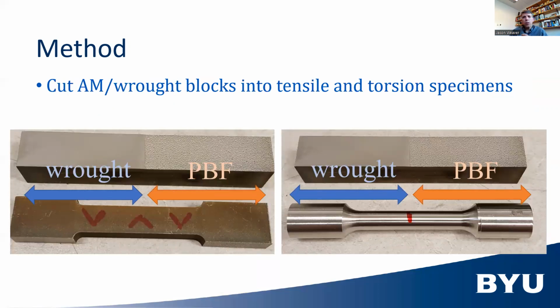After we had created these blocks, we machined them down into conventional samples. So we were able to make tensile samples and torsion specimens. And for each one of these, you can see that half of the specimen is the wrought material and half of it is the additive manufactured powder bed fusion material.